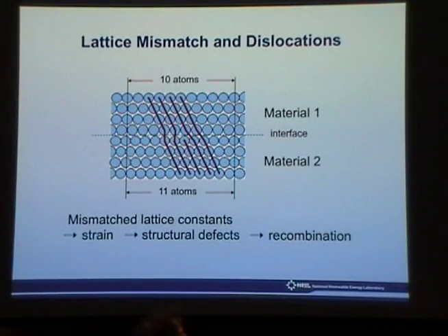So this is a sketch trying to illustrate the problem with lattice mismatch. Here you have two materials, material 1 and material 2, one on top of each other. If you count the number of atoms between this vertical line and this vertical line, there's 10 atoms here, there's 11 atoms here. So imagine for a second what happens when you start to grow. You start with material 2, and now you're depositing material 1. When you have only a monolayer, it strains itself to be lattice matched, right?